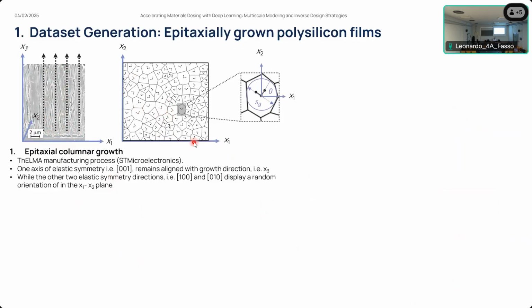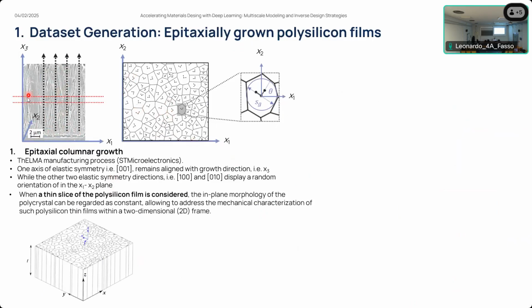Moreover, if we analyze a very thin slice of this material, we realize that the in-plane morphology of this polycrystal can be regarded as a constant, and therefore we can address the mechanical characterization of such polysilicon thin films, in this case, within a two-dimensional frame.